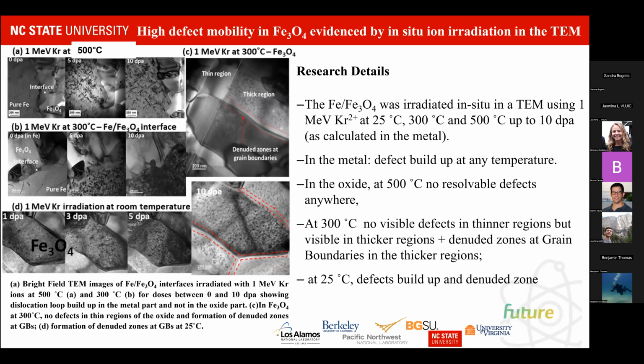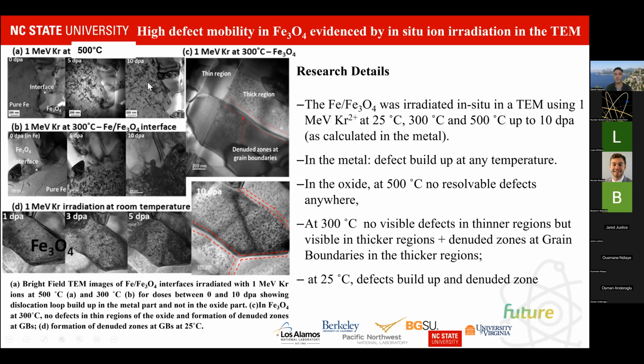What we were able to see by doing systematic experiments in the same conditions but at different temperatures is an effect of temperature, but also a difference between the metal region and the oxide region. We started with 500 C, and the major difference was that defects would form and grow in the metal, while in the oxide nothing could be observed. At first, we started wondering whether it was something intrinsic to the oxide or not. We did the same experiment at 300 C, and same thing. The oxide regions were deprived of defects, while the metal showed formation and growth of defects.